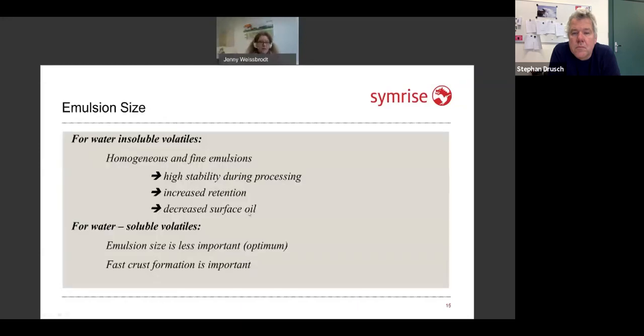Let's go for the emulsion size. Emulsion size in this case means the distribution of your active within your matrix. Of course, for water-soluble volatiles, it doesn't make any difference. You put it in, it will completely mix up with your continuous phase with your water. You don't need to homogenize or something like that. The emulsion size is not important because it's not there, at least. In this case, just a fast crust formation during the drying process is important.